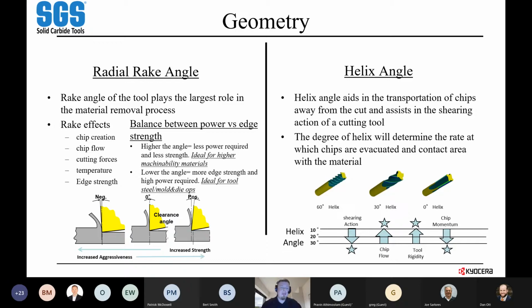Lower angles in that neutral into negative territory are going to be about edge strength. They are going to require more power, but they're going to have a significantly stronger edge that's going to handle just more abuse ultimately. But like I said, it will take more power, a little bit more horsepower requirement on the machine, and or more rigid setups to be able to take the force behind that cut. So this will be ideal for tool steel, mold and dies, as well as some of your high temp alloys. A lower positive to neutral, maybe even into negative geometry can be beneficial in some of those as well.